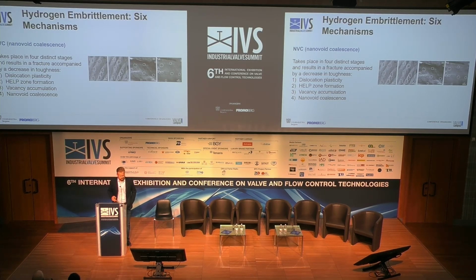And I think this is the last one in terms of embrittlement. You have the NVC, so the nanovoid coalescence. This is very similar to the first one. So you're having basically the merge of different spots where hydrogen concentrated inside the metal. It actually starts to merge in bigger voids. Those voids actually cause the failure of the structure.